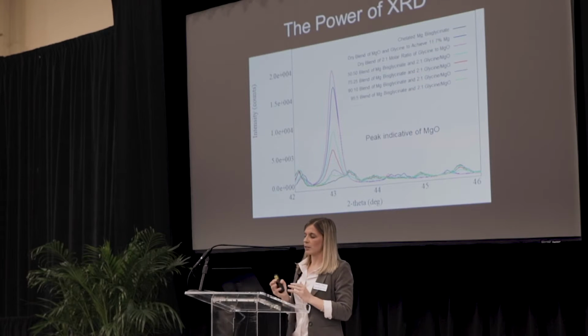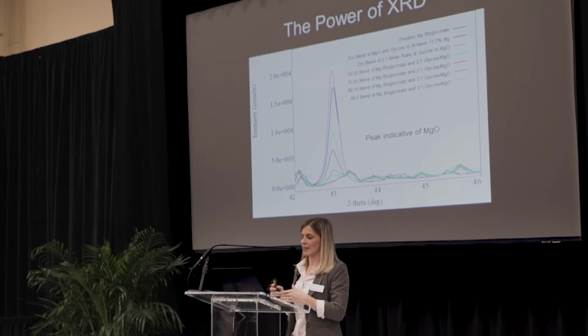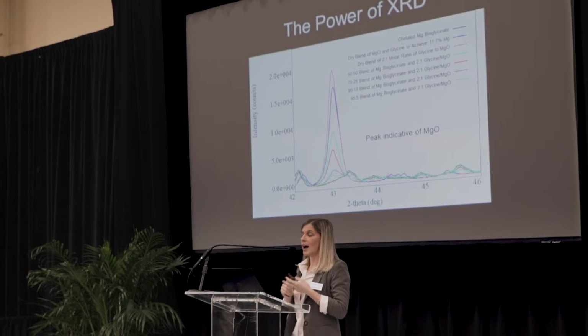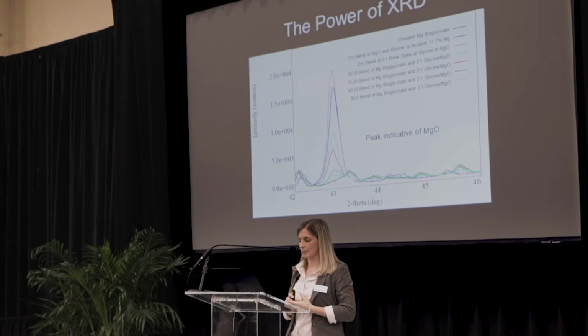And so this slide really shows you the power of XRD. For any scientists in the audience, this slide might be of interest to you because I think this is truly a beautiful piece of data. What we did at Innophos is we took a lot of different samples, and we wanted to gather the data on all these different samples to see could we tell the difference between them. So we created a 50% reacted product, a 75% reacted product, 90%, 95%. These different samples we made so we could check them by XRD.